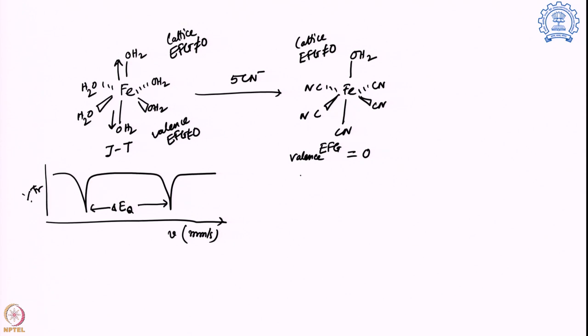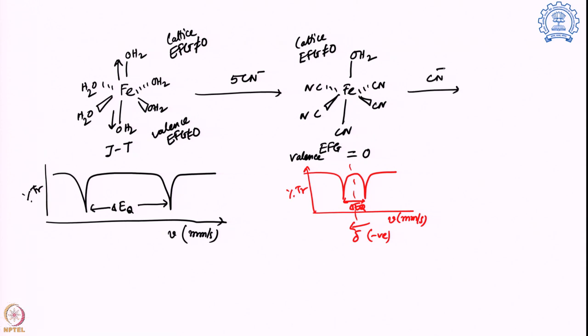So that is why over here I am expecting that this system is going to show a small shifted value of quadrupolar splitting. So it will be much smaller, and not only that, the delta value is going to shift towards a more negative direction, because now the cyanide with their all pi back bonding is going to move the d electron out of it. And finally, one more cyanide moves in, replacing the final water molecule.